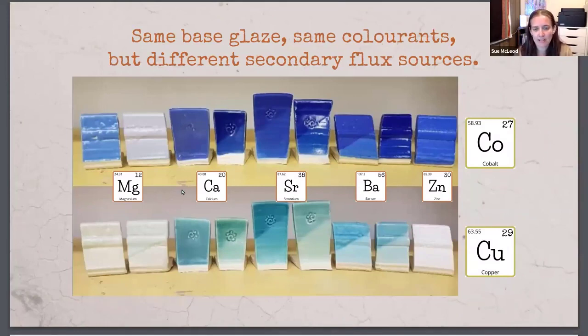Now, here's an example from the Art of Glaze Chemistry course. Same base glaze, same colorant, but different secondary fluxes. Just a reminder, the secondary fluxes are magnesium, calcium, strontium, barium, and zinc. So all of these are cobalt, same base glaze, but this one is using magnesium as the secondary flux. And I use material substitutions to replace one flux for another, so it totally changes the chemistry. Calcium is these two, strontium is these two, barium, and then zinc. So you can see another range of colors that you can get from one colorant, depending on the chemistry of the base glaze that you add it to.